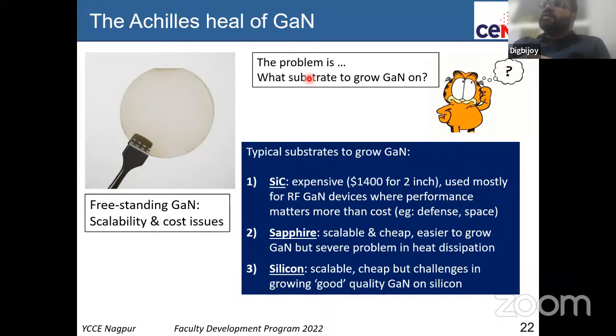Silicon is better in managing heat, and you can grow gallium nitride on silicon. However, silicon is a very different kind of material, and growing is very, very challenging. The defects and dislocations of gallium nitride on silicon are a recurring problem, and that leads to reliability issues, performance issues in gallium nitride devices. But then if you grow GaN on silicon, you can beat the cost, or you can come very close to the cost, because you can make it scalable. You can make large area.